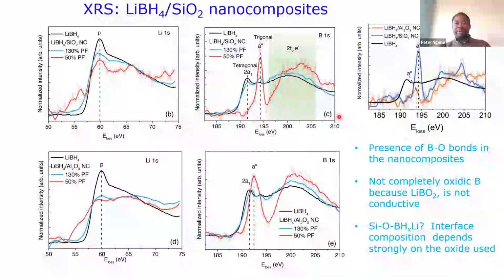And I did mention this already before. If you even go to a very low concentration of our sample, that is just 50% loading, which is very, very close to the interface, we can't see the bulk-like one, and then of course there's no signature of the bulk-like lithium borohydride. Rather, we can see this new peak, that is the trigonal boron. And when we compare the alumina and silica, you can see a clear difference between these two.